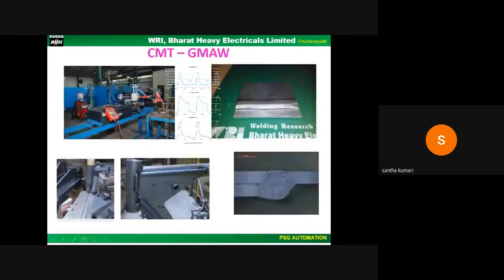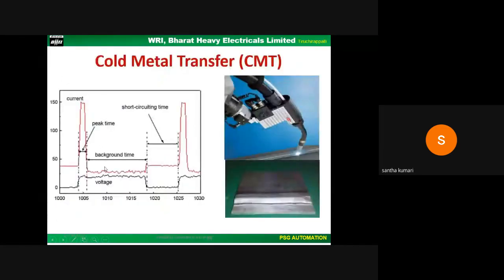Here CMT is another, we can say, boon to the welding users. It has been added with another digital control technology, feed forward motion of the torch mechanically, besides the waveform controls. You may be able to see the application of CMT as a replacement of the conventional short circuit modes of metal transfer in automotive applications, with which productivity improved by more than 60%. Here is a peculiar waveform of the CMT process. The added advantage of this process is that the power is reduced nearly to zero. The current is reduced to zero during the droplet transfer.